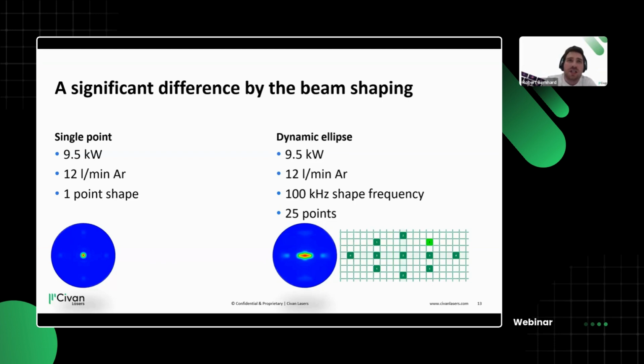And when we're talking about high-speed welding, my definition of high-speed welding here is 30 meters per minute, so 500 millimeters per second, and that's our target welding speed we wanted to achieve. And as a starting point, we wanted to go with just a single dot. That's to make it somewhat comparable. But to spoil it a little bit, the single dot is no way of getting this welding done correctly.